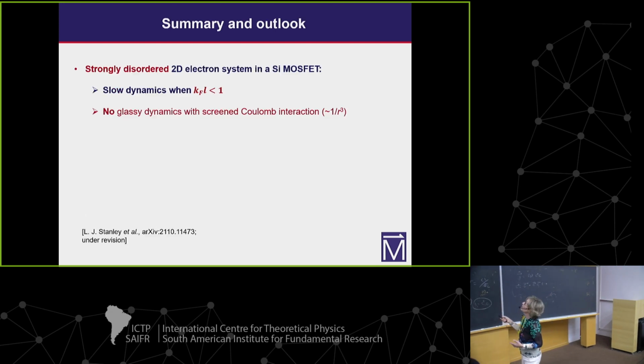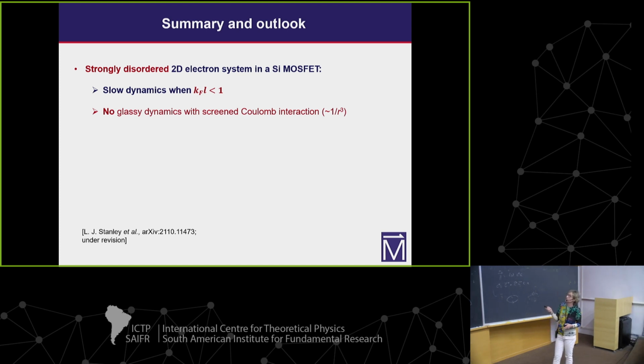So our result is consistent with those that claim that in this case the system can be in the MBL regime. So basically, I showed you that in strongly disordered 2D electron systems, when KFL is less than 1, we always observe slow dynamics. In the case of long-range interaction, the dynamics is glassy. This study was actually started many years ago, and the original question that motivated our work was whether glassy dynamics can persist when you screen the Coulomb interaction. So we have our answer here: no, it does not persist, at least not in the case of a dipolar interaction.